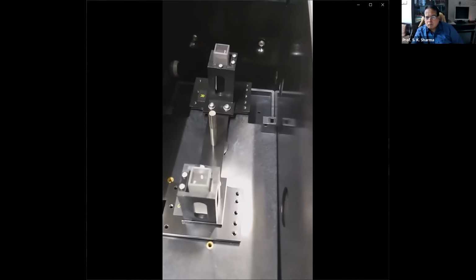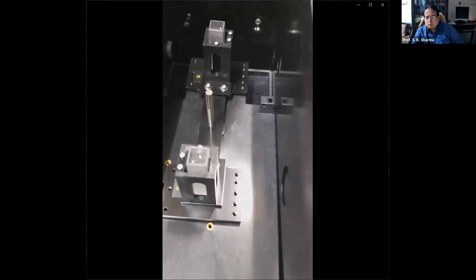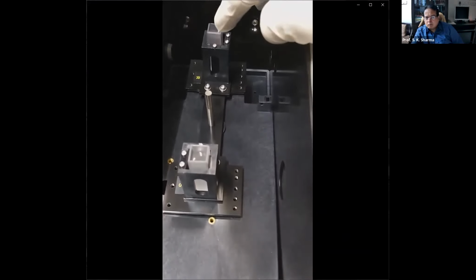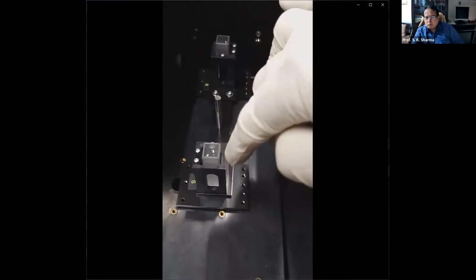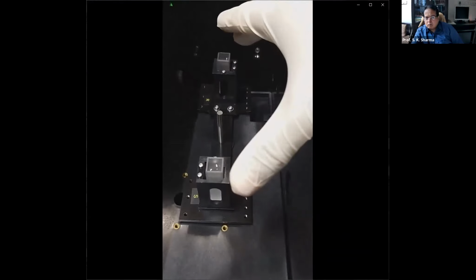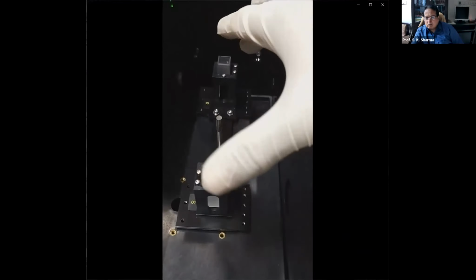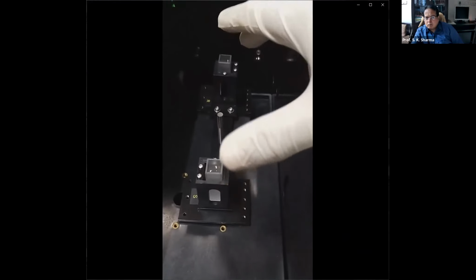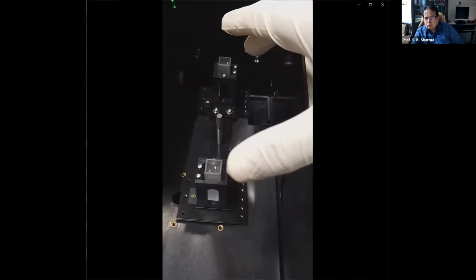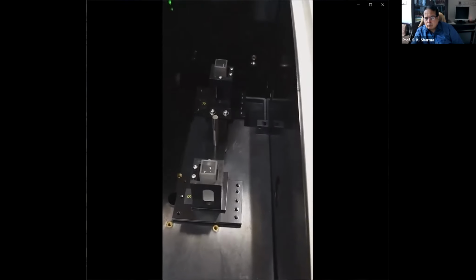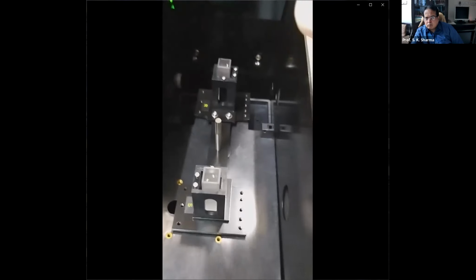So we have put the two cuvettes. One is under reference sample, and this is for the test sample. So both cuvettes are having DI water, deionized water, and we will test them.